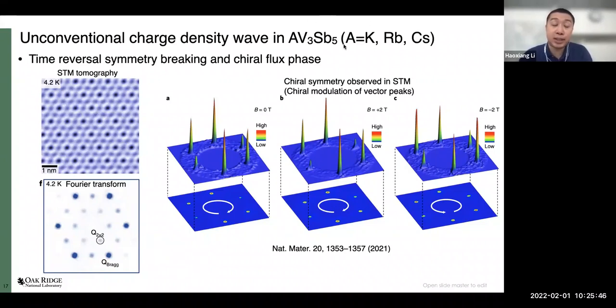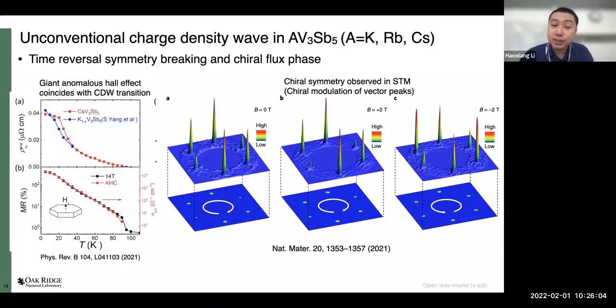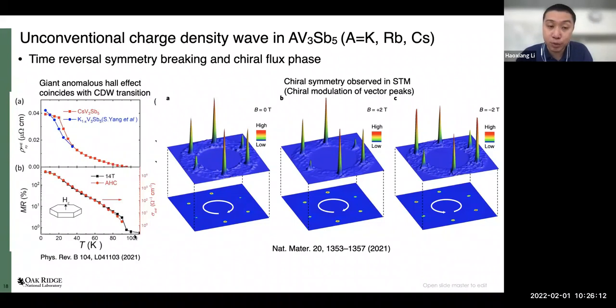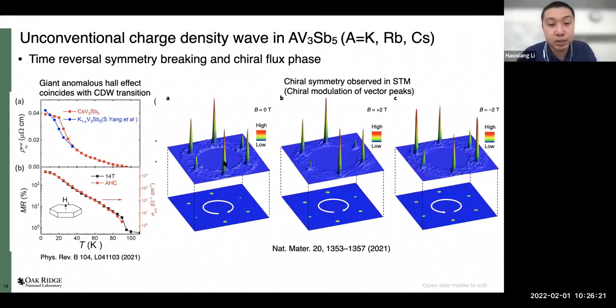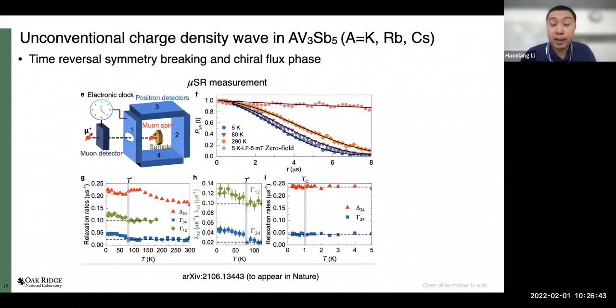However, this Kagome material has no magnetic compounds, and neutron and muSR measurements have confirmed there is no static magnetic order, nor any local magnetic moments inside these materials. In this completely non-magnetic material, there is an anomalous Hall effect rising together with the CDW transition. Inside the CDW wave vectors observed from STM scanning tunneling microscope, it should also show time-reversal symmetry breaking. This would be the first discovery of time-reversal symmetry breaking conducted by a charge density wave, making this very interesting among the many complex intertwined symmetry breaking orders.